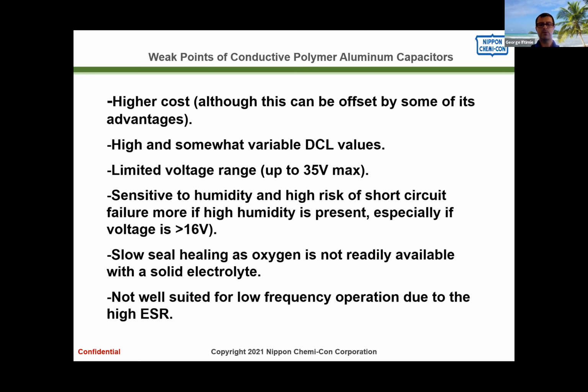On a liquid part or a hybrid, any spike or any damage to the oxide layer will tend to be repaired very quickly. On a polymer, it may take significantly longer. Something that will take seconds on a hybrid may take hours on a polymer to heal. So you do have to worry about cumulative types of damage effects. You're kind of chipping away over and over again until eventually you may have a problem.